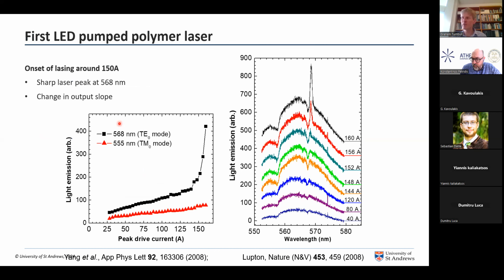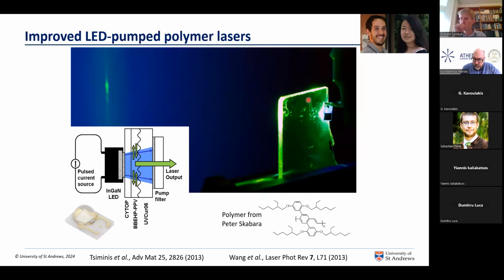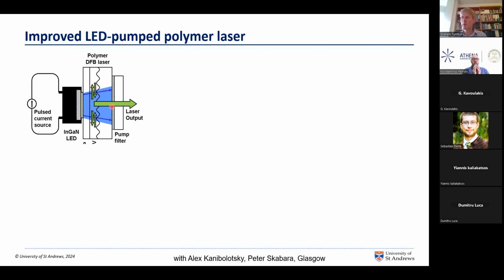And so this first laser, about 15 years ago, just managed to squeak above threshold, and we got this typical characteristic where you get this higher slope appears and a narrow peak starts to appear in the spectrum, showing the onset of lasing. With some further work, we were able to make these a bit more robust, and this is work that was carried out by Georgios Tsiminis and Christina Wong at the time, where we could get a nice green laser beam being emitted out of our organic semiconductor laser that's pumped by an LED. So that's LED pumping, but there's still some challenges.